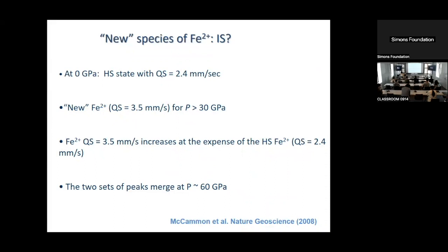My last question, I'm sorry to hold everybody up, is particularly as one gets away from totally dilute iron, if one gets to 25% or 15% or something. I understand the different spin states and different orbital states have different local octahedral volumes. And because the orbitals are involved, there is an anisotropic, kind of Jahn-Teller thing. So that suggests that the different states may be coupled by a strain, which can propagate over longer distances.